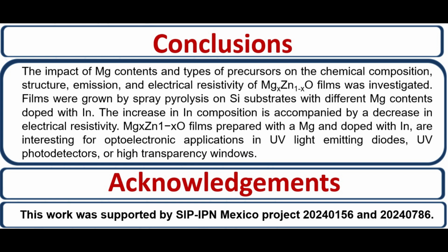Conclusion: X-ray diffraction analysis shows wurtzite structure. Moreover, the shift of peak 002 suggests a relationship between elastic strain, not shown here, and electrical resistivity. In addition, when indium is 4% for both magnesium contents, the minimum of resistivity at minimum size is achieved. However, the maximum of energy gap is reached at 3 atomic percent while maintaining an optical transmittance of 85 to 90%. The increase in indium composition is accompanied by a decrease in electrical resistivity.